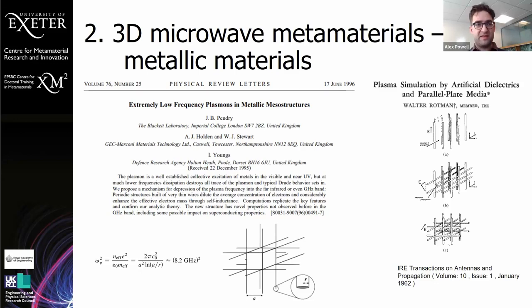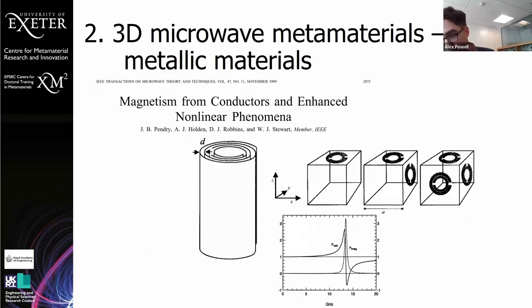So you can change when a metal stops behaving like a metal. Usually for natural metals, that tends to be somewhere in the high visible or the ultraviolet. But here we can bring that plasma frequency, that transition between metallic and non-metallic behavior, all the way down to the microwave. And that's just using a 3D grid of wires. But even that is actually quite difficult to make in 3D, as I'll talk about in a second. And this gives negative permittivity, another important thing to note around your region of interest.